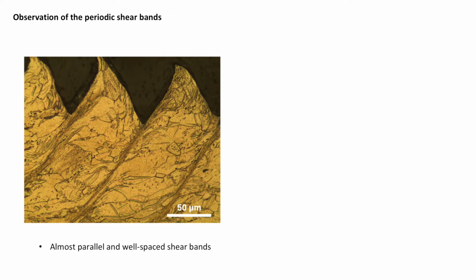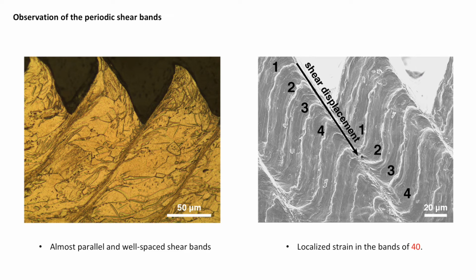Dinaka's group then did optical microscopy looking at the cross-section of this metal strip. After mechanical polishing and etching, they saw those bands in the titanium metal strip. Between the bands, the intrinsic or original microstructure is more or less retained. This tells us a lot of deformation happened within the bands, not between the bands. On the right is an SEM image, and micromarkers or scratches were placed on the metal before doing the cut. Again, you can see a sharp, abrupt disruption of the continuity of those scratches at the shear bands.